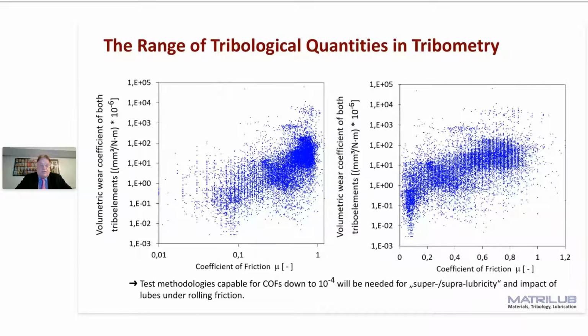The same for the coefficient of friction. You have at least up to 2 orders of magnitude. And if you look at the actual research on superlubricity, you go down to 10 to the minus 3, and if you consider rolling friction, you go down to 10 to the minus 4 for the coefficient of friction. This makes it complex and complicated from the metrological point of view to mimic all in one test equipment, which is nearly impossible to do. And this gives you an indication why you need so many different test machines which can be adjusted for different load ranges.